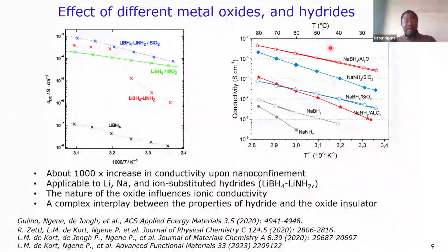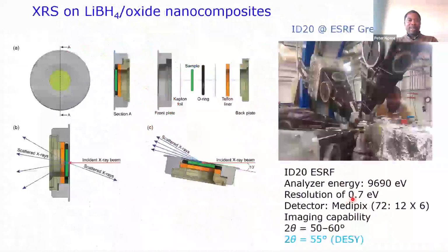And this is what we see for different kinds of scaffolds, which means that there's a complex interplay between the properties of the hydride and the oxide insulator. So we wanted to understand what is happening: why, when you add this insulating material that does not have any form of ionic conductivity to an ionic conductor, you have orders of magnitude increase in the ionic conductivity. These are insulators, so the reverse should be expected. So we wanted to understand this a bit more.